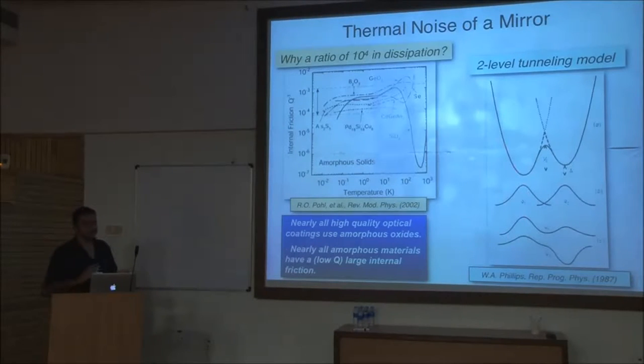And, these low energy, sort of, milli-eV excitations allow it to reconfigure itself from this configuration into this other one. And, this theory that I'm pointing out here, this is sort of a phenomenological theory. But, they use it, it seems to have a remarkably good predictive power. And, so, although it's not a true microphysical theory, it's the one people seem to use. So, anyway, everything is bad. All amorphous thin films are bad. Fused silica is, as Peter was saying, it's pretty anomalous. When you get it to several hundred degrees, even the thin film seems to have a very high Q. Yeah. Another mystery. Anyway, we're not here to solve these mysteries. We're just noting that they're there.